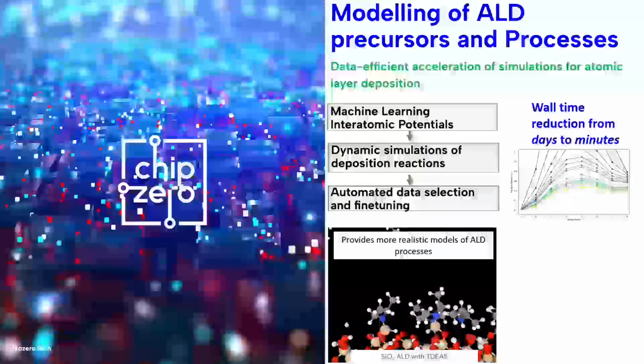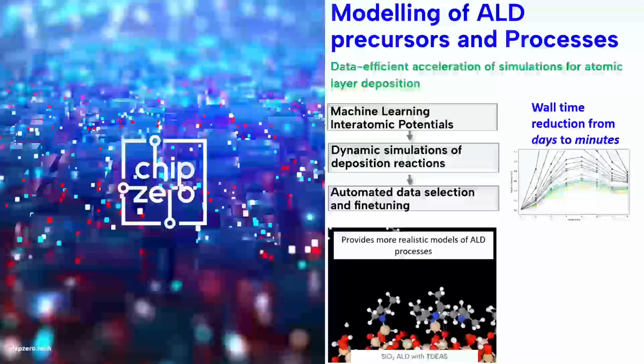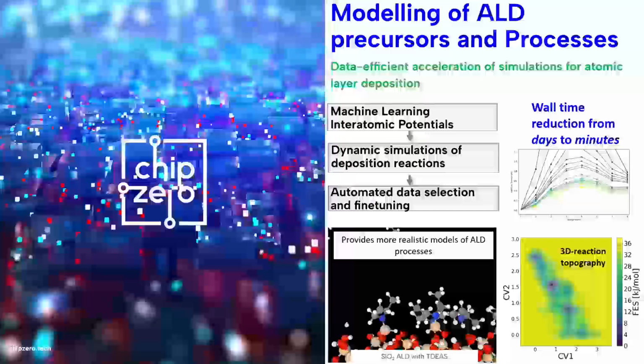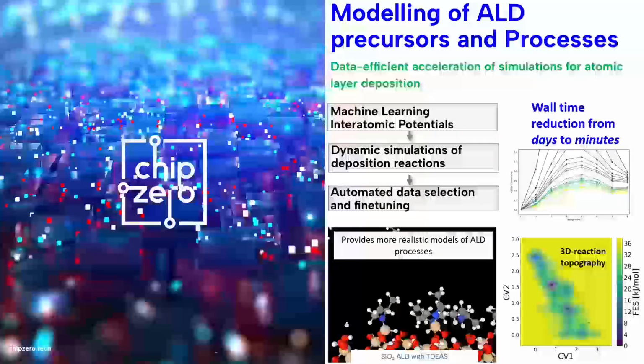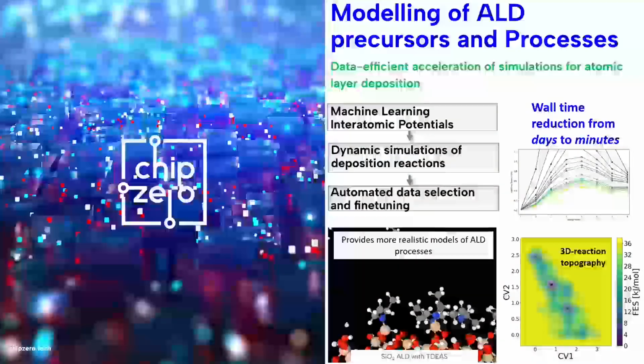And so this, compared to traditional methods such as DFT, reduces the wall time from days to minutes, generally speaking, which means that we can spend more time on looking at the chemistry, on trying to develop precursors that are suitable for given materials, than waiting for computations to finish. And also as a side effect of these simulations, we get these 3D reaction topographies or free energy profiles, which we can then use to compare different reaction pathways.